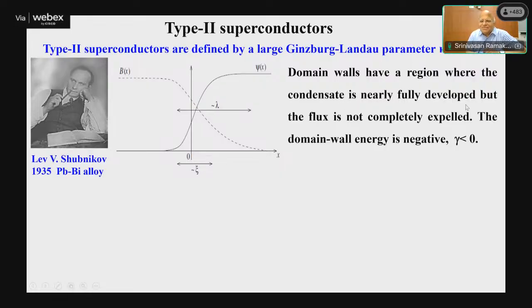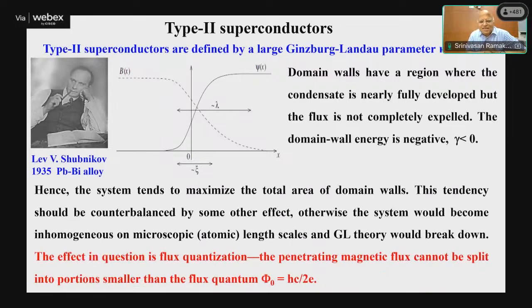Domain walls have a region where the condensate is nearly fully developed, but the flux is not completely expelled. So the domain wall energy is negative. So it is favorable to form these domain walls in type 2 superconductors. So how does the field go inside the mixed phase? Does it go randomly or does it go everywhere? How does that go? So the system tends to maximize the total area of the domain walls.